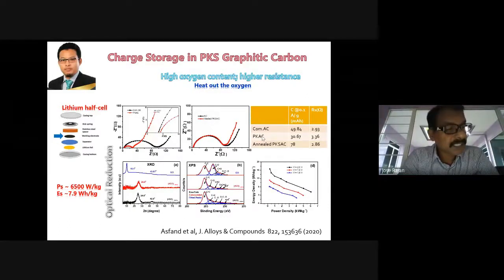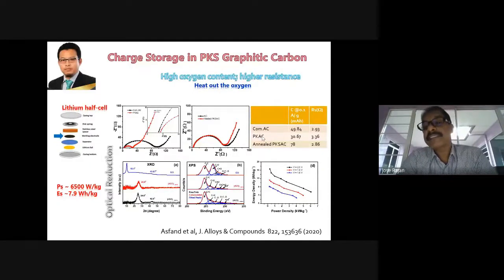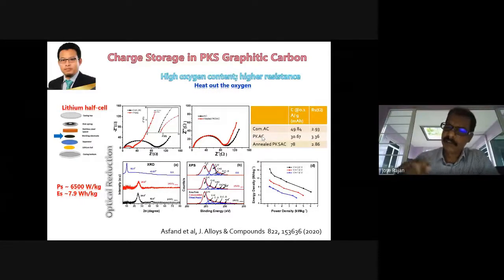There could be many chemical methods. We used two physical methods. The first method is to heat the oxygen out, so we heated it, annealed it. When we annealed it, you would see in that table that the capacity is much higher than the commercial activated carbon, and the resistance is much lower too. And the next thing that we did is we optically reduced them. We used a laser, laser heating, to remove oxygen. And these papers were recently published in this journal. You can browse it and read for details.